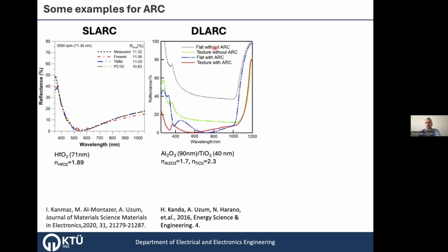This dashed line measurement is the flat silicon surface without anti-reflection coating, and you see that the average reflectance is around 40%, right? And if you texture it, without anti-reflection coating, only texturing, you can decrease this reflection to this green dashed line, okay? And in this case, we apply a double anti-reflection coating. If we apply anti-reflection coating on the flat surface, you can decrease it like this. And if you apply it on the textured surface, you can further decrease the reflection like this red one, okay? And this is the case for aluminum oxide, titanium oxide anti-reflection coating.